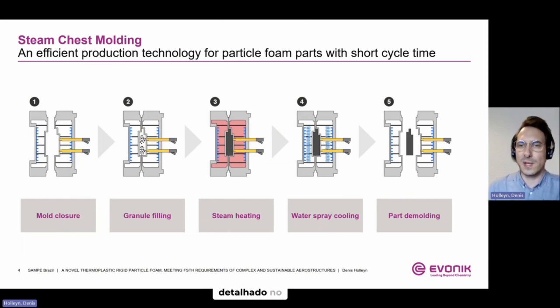And now let us have a more detailed look into the foam part production process itself. This process step consists of 5 single steps actually. The process starts with the mold closure. After this, we fill in the preformed particles that we have seen on the slide before. And once the mold is fully filled, we can apply the hot steam. This will make the particles expand and fuse together. After this heating cycle, we can start with the cooling. In our case, this is a water spray cooling, which helps to cool down and stabilize the foam part. In the last step, we can demold the net-shaped foam part and use it for further processing, as for example, as the sandwich core.